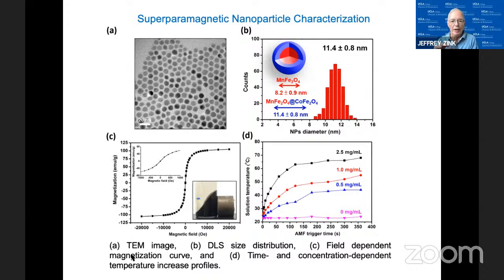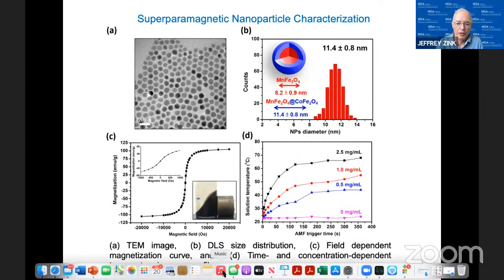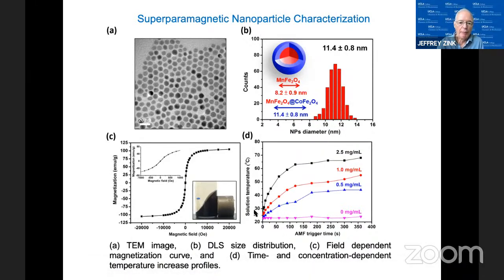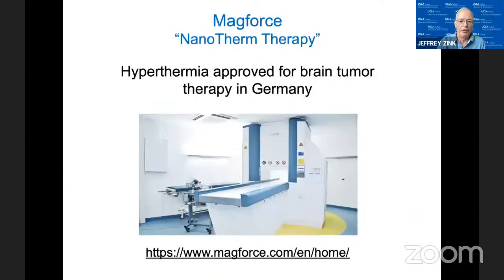So the entire magnetic particle is one domain. All the spins line up in the domain, and you can get very high magnetizations. And then when you apply the magnetic field, by a mechanism I'll describe next, that interior core can heat up. So we do show here how the temperature of the whole bulk solution can be heated under very high fields. And from that, we can measure the amount of heat generated by the particles for certain conditions of the magnetization and control it. Okay, so that's the core that we're going to be using in these studies.